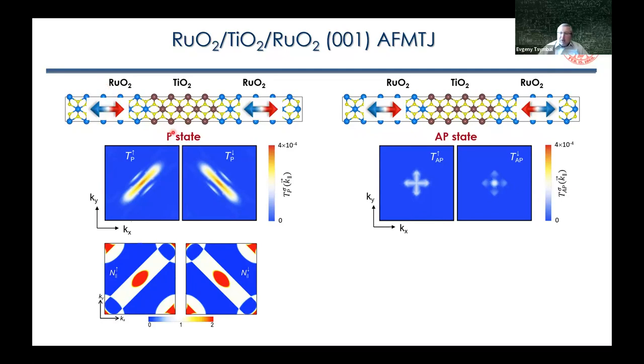What I'm saying is that if you go back to this idea of spin-dependent Fermi surfaces, this is driven by magnetic space group symmetry. So if the magnetic orientation is not along 001, but along, let's say, the X or Y axis, then the magnetic space group symmetry will be different. I don't think so. The standard magnetic space group is irrelevant here if there's no spin orbit coupling. It doesn't matter which direction the spins are pointing. That's true, yes. So you're talking about the presence of spin orbit coupling.